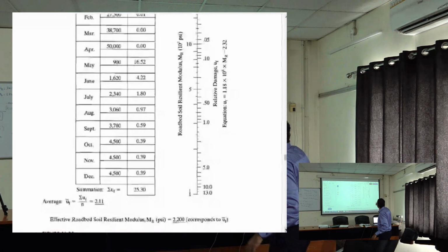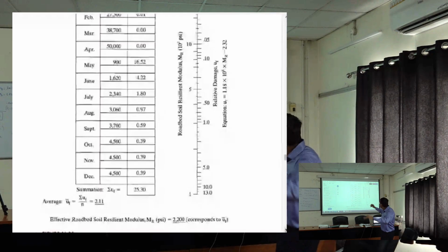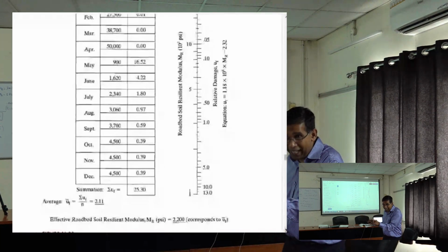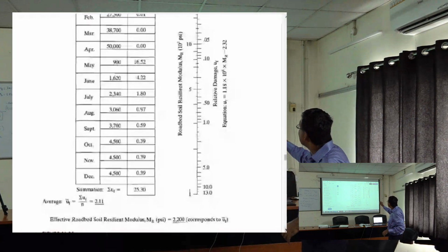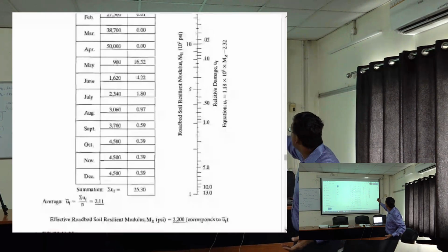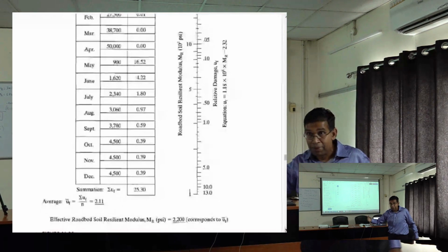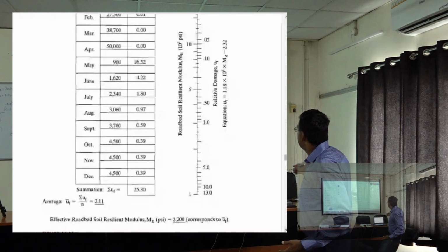I'm going from 38,000, 50,000 to 2,200. Instead of looking at it the other way, I'm not taking the average of those numbers. If you try to average them, it will be much greater than 2,200. So you are almost very close to 900. Does that make sense? This 900 is pretty much dictating this number, like it or not. I'm dropping from a high of 50,000 to 2,200 because of one single number that is just dictating the damage.